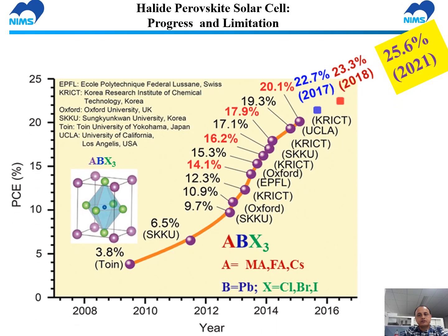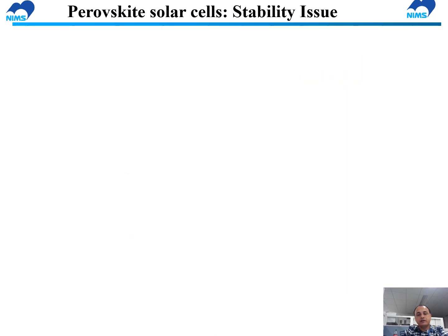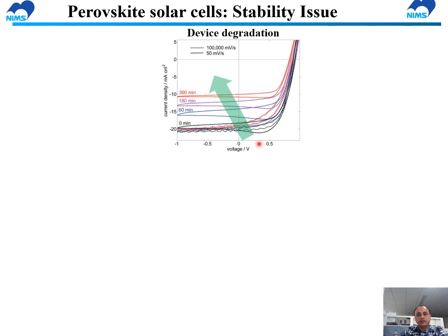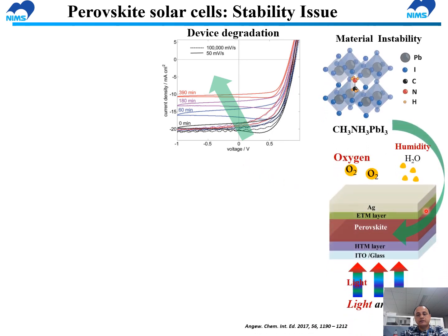As we know, perovskite solar cell has improved device efficiency from 4% to 25.6%. However, the device is not as stable as other types of solar cell. So perovskite solar cell has to be stabilized for its commercial application. As we see, device performance degrades with aging time. If we see the device stability, the material itself is not so stable.